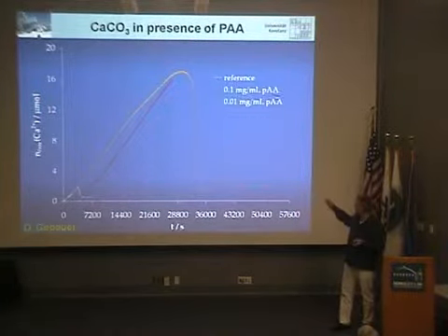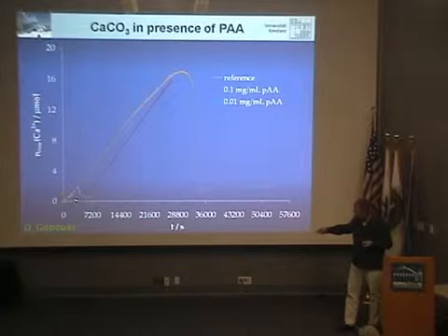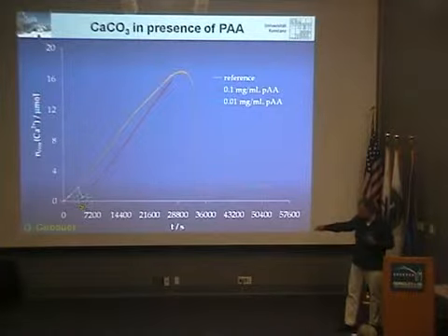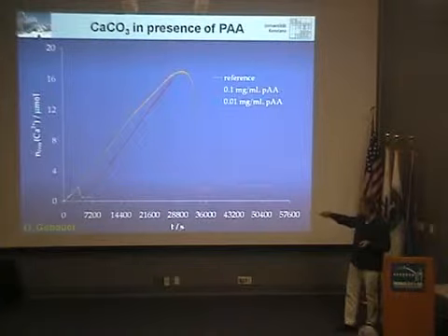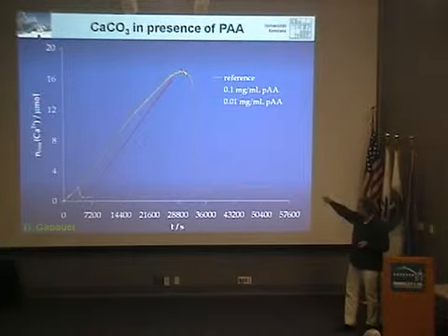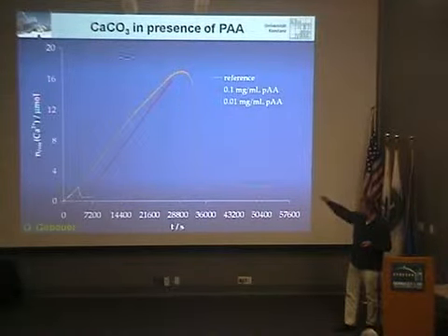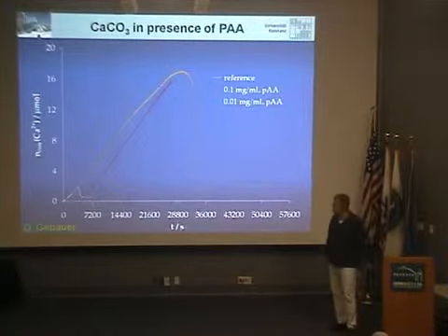And if you add polyacrylic acid, which is a well-known scale inhibitor, so a polycarboxylate, which will bind calcium, you will see it's already binding calcium straight at the beginning. So if I add calcium, it's bound. And I can quantify that by extrapolating the curve. I know exactly how much calcium is bound by polyacrylic acid. Then the curve rises. And you see that nucleation is significantly inhibited in time compared to the reference experiment, and also in supersaturation. So the calcium concentration at which nucleation occurs is much, much higher in presence of polyacrylic acid.